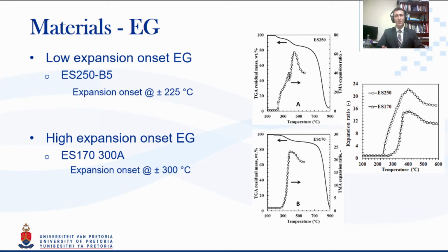So this graphitic structure is not as stable as natural graphite or natural graphite with very even distribution of intercalated molecules. One of the things that we noticed, as you'll see with expandable graphite here, is that it almost doubles the amount of expansion of ES170, the high expansion onset material, because there is a 27 times higher oxygen to sulfur ratio in this material, meaning there's a lot of extra oxygen and CO2 gases that get released in addition to the SO2 naturally released from expandable graphite, which have some really positive results actually if one desires to flame retard at that onset temperature.